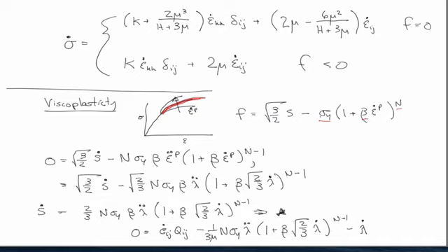So I have to actually solve this differential equation to get lambda, then I can plug it back in and eliminate it, right? And so that's why this is just sort of the next more complex case, and already we've approached something that we have to go to a computer to solve. That's why you see very few solutions in plasticity.